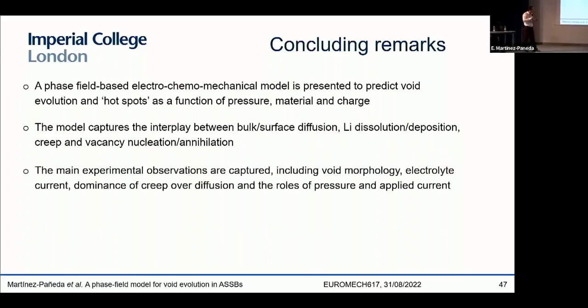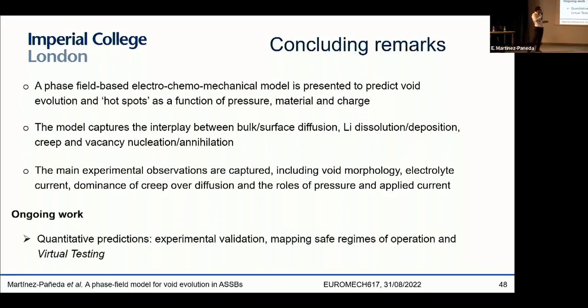And then I hope to have convinced you that the model provides good qualitative agreement with experimental observations, so we can capture the void morphologies that we see in the experiments. We can capture the localized current hotspots that we suspected are happening in experiments and leading to the nucleation of those dendrites. And we can capture the interplay between creep and diffusion and the role of the applied pressure and the applied current. So this is our first attempt at modeling this exciting and complicated phenomenon of voiding, current hotspots, and dendrites in solid state batteries.